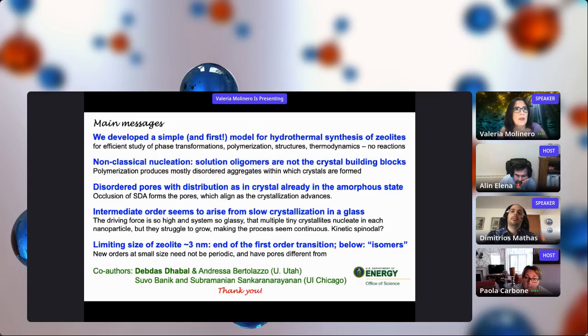Absolutely. This is a great point. The pH needed for zeolite synthesis is about 10, 11. And during the synthesis, the pH goes up because the reactions free more OH groups. But if you take it at any stage and you cool it down to pH 3 or acidic or even neutral, you stop the crystallization. And that's the way that people have made amorphous zeolites.